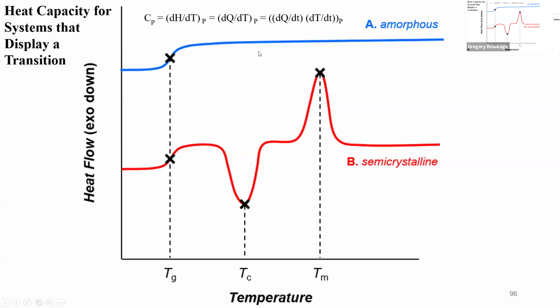Right, so that's simple. Basically, if you cool it down any faster than that, it has kind of residual strains and stresses in it that get locked in. And if you heat it up from the glass, you'll see that those relax. And when those relax, there's an enthalpy associated with it. So it's a transition that has zero enthalpy, but these kind of locked-in structural things give rise to something that looks like an enthalpy transition. So it'll have a hump on it, and that hump has to do with the speed that you cooled it. The faster you cool it, the bigger the hump.